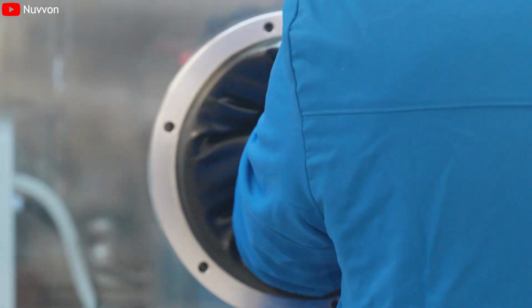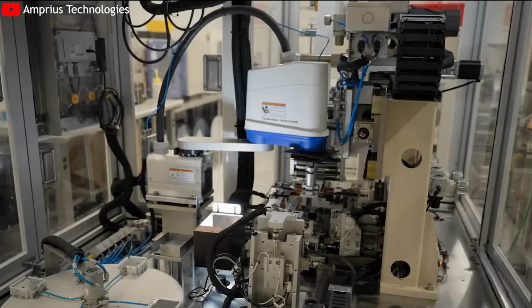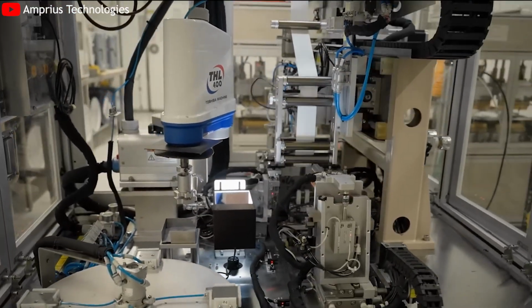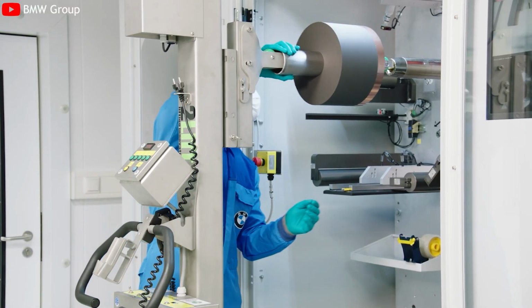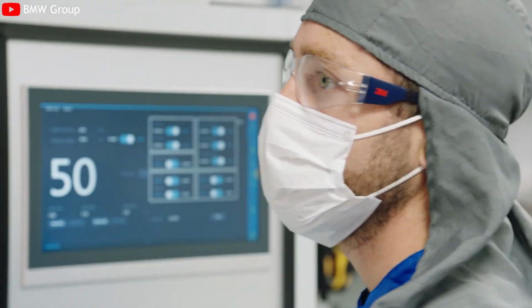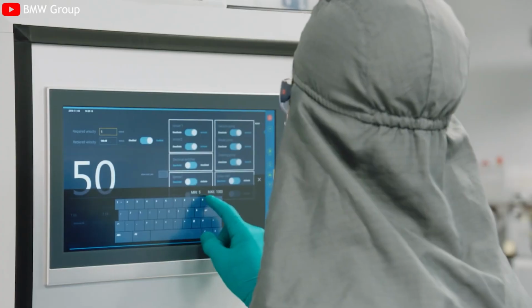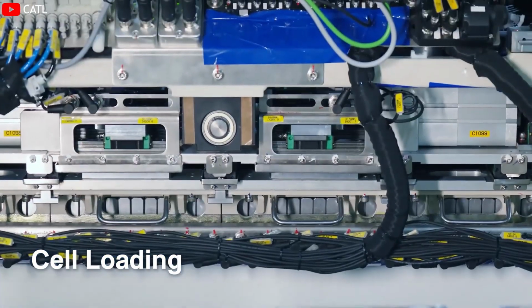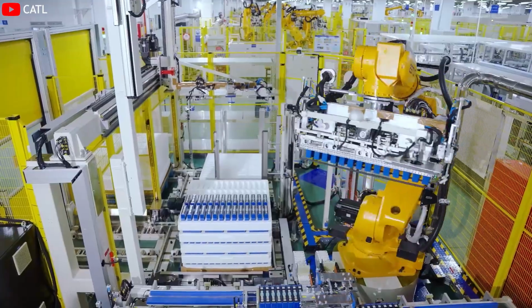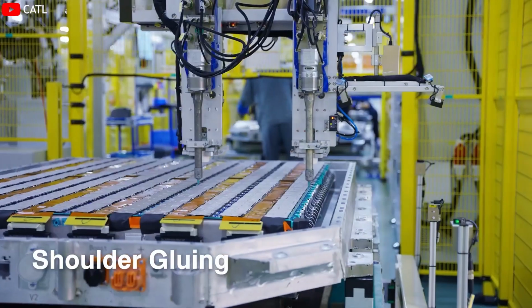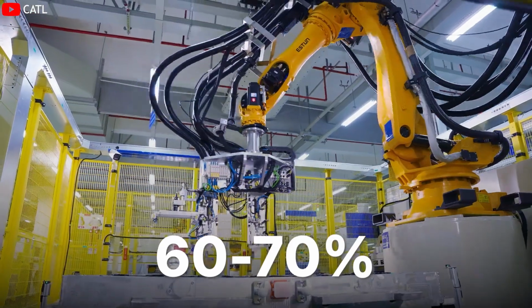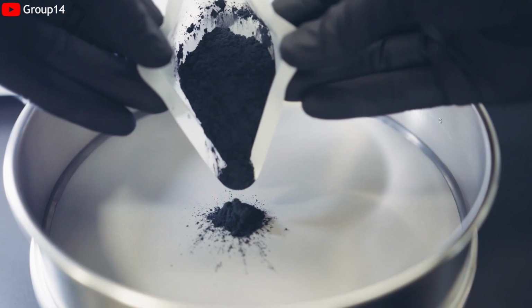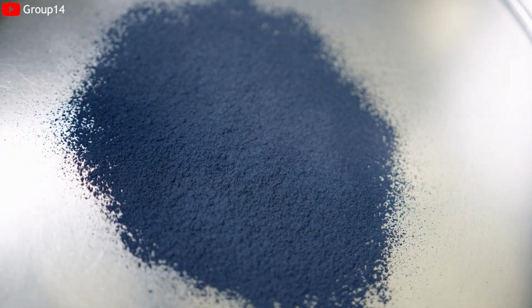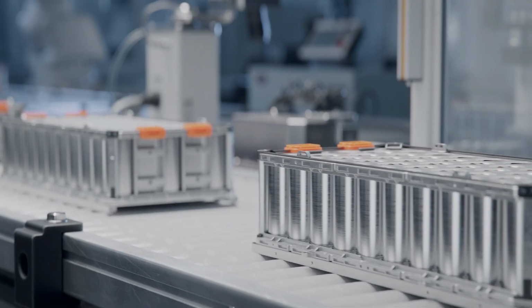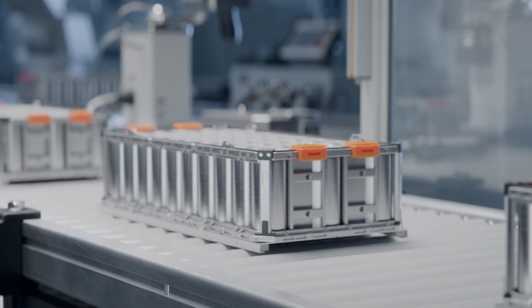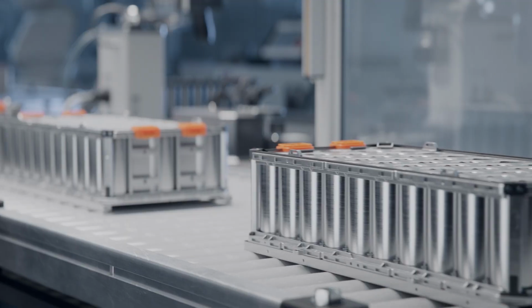If the benefits are so compelling, why did Tesla hesitate? Because none of these advantages matter if manufacturing yield collapses. A modern wet coating lithium-ion factory typically requires yields of 95 to 98% to remain economically viable. Even at that level, battery production is capital-intensive and margin-sensitive. Early dry cathode lines reportedly struggled to exceed 60 to 70% yield. At those levels, scrap rates overwhelm every theoretical cost saving from solvent elimination. Rework, recycling, downtime, and warranty risk erase the economic case almost instantly.